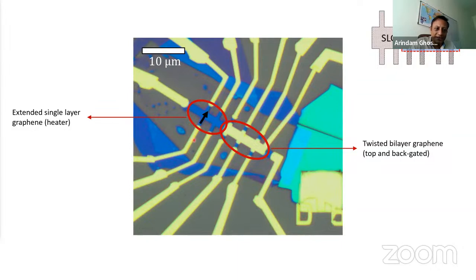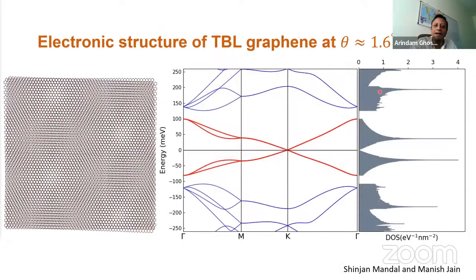And then we pass a heating current in this direction to create a temperature difference along this and measure the resulting thermal voltage. Okay, the experiment that I'm going to show you was done at around theta, the two layers are rotated with respect to each other by about 1.6 degrees. The corresponding band structure calculation was done by my colleague Manish Jain and his student Shinjan Mandal. And their calculation and the density of states are shown here.